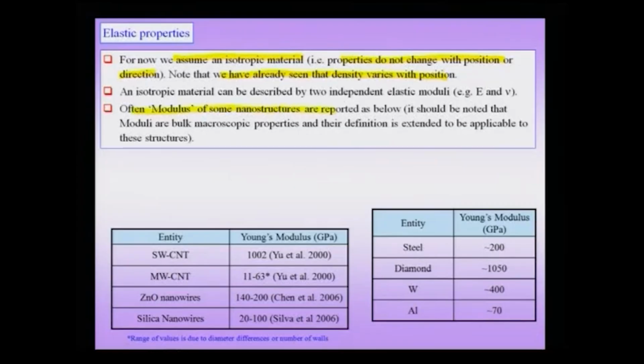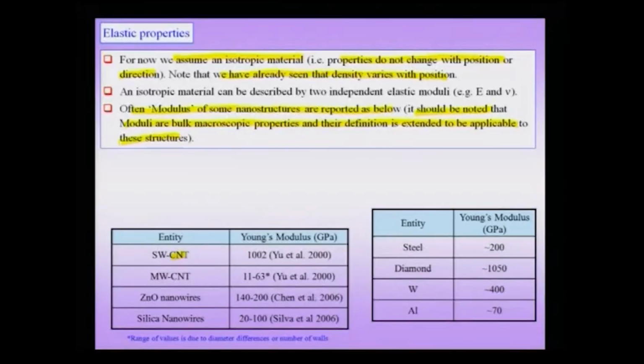Often modulus of some nanostructures are reported below. It should be noted that moduli are bulk macroscopic properties and the definition is extended to be applicable to these structures. So, we should note that modulus as such is a bulk macroscopic property. That means, it is an average over a large number of atoms. And if I am going to be describing modulus of a small entity like a carbon nanotube, which could be a single walled or a multi walled carbon nanotube, or I am talking about a zinc nanowire wherein the number of atoms are much limited, then I am actually extending the definition of the bulk elastic modulus to some of these smaller entities.